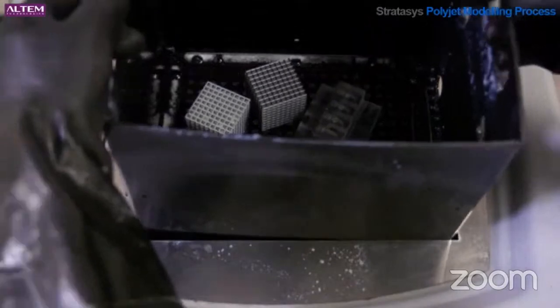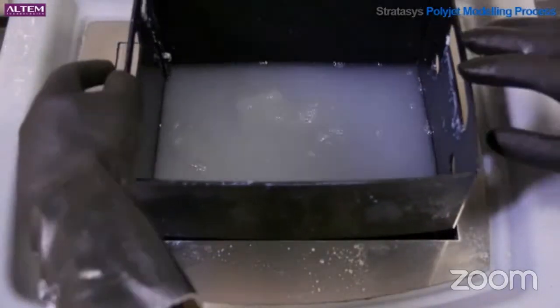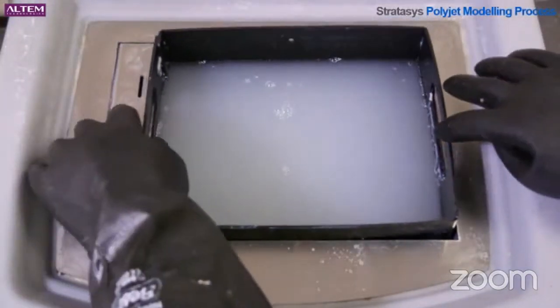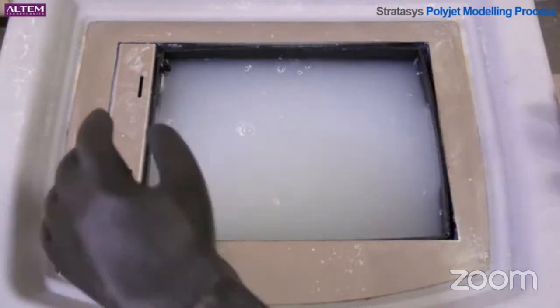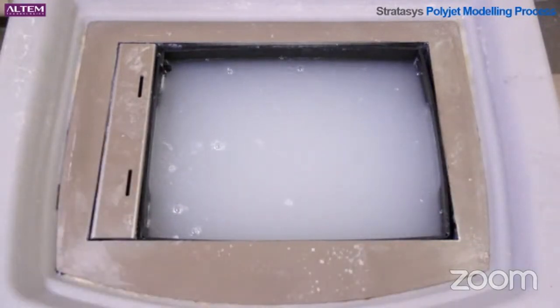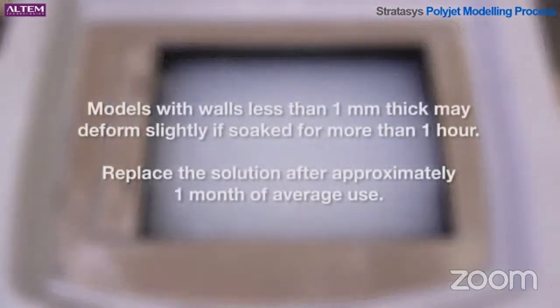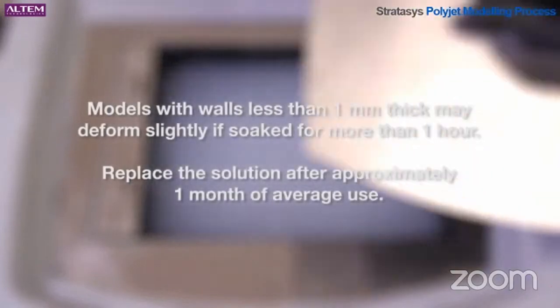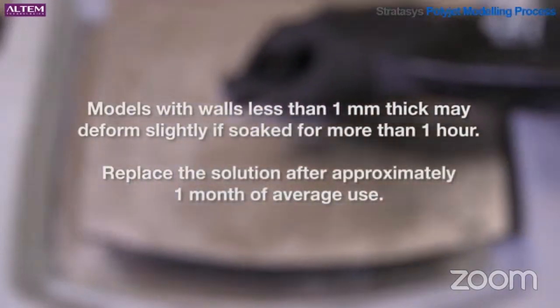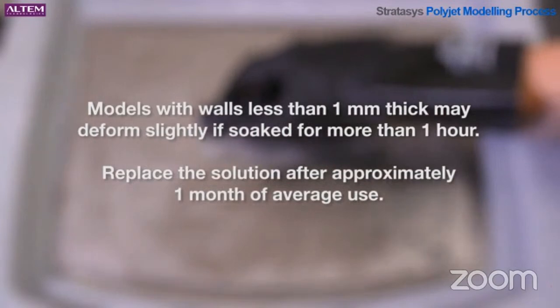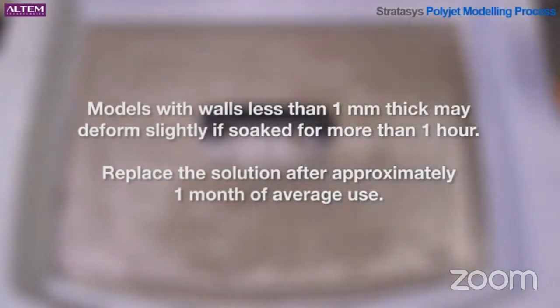Allow the solution to cool to room temperature and soak the model for 30 minutes to several hours, depending on how delicate the model is and how much support material needs to be removed. Models with walls less than 1 millimeter thick may deform slightly if soaked for more than 1 hour. Over time, SUP 706 dissolves into the solution, reducing its effectiveness. Replace the solution after approximately 1 month of average use.